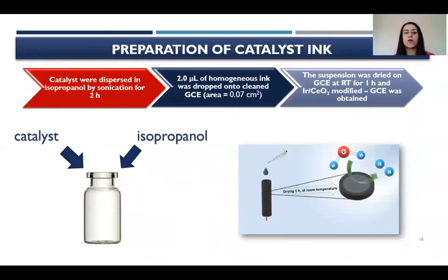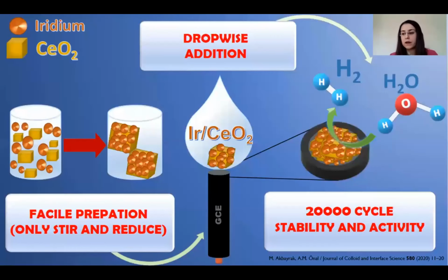The obtained catalysts were dispersed in isopropyl alcohol by sonication for 2 hours. Then 2 microliters of the homogeneous ink was dropped onto the surface of a clean glassy carbon electrode. The suspension was dried on the glassy carbon electrode at room temperature for 1 hour. And finally, the iridium ceria modified glassy carbon electrode was obtained. We prepared iridium ceria with a facile method. Then we attached the catalyst onto the glassy carbon electrode by drop casting, and iridium ceria exhibits outstanding activity and stability towards the hydrogen evolution reaction.